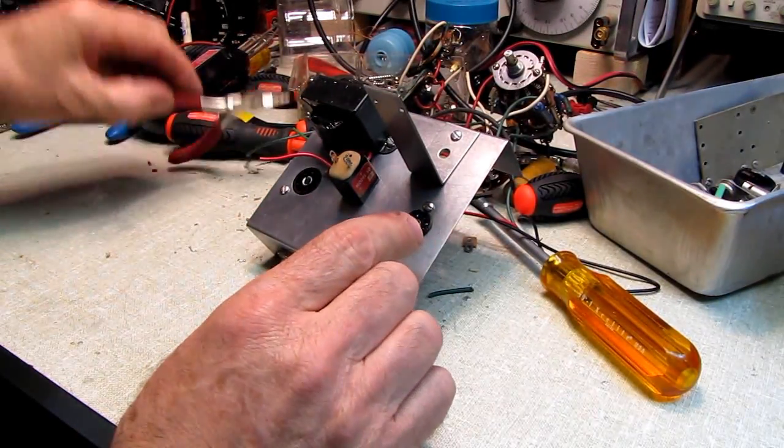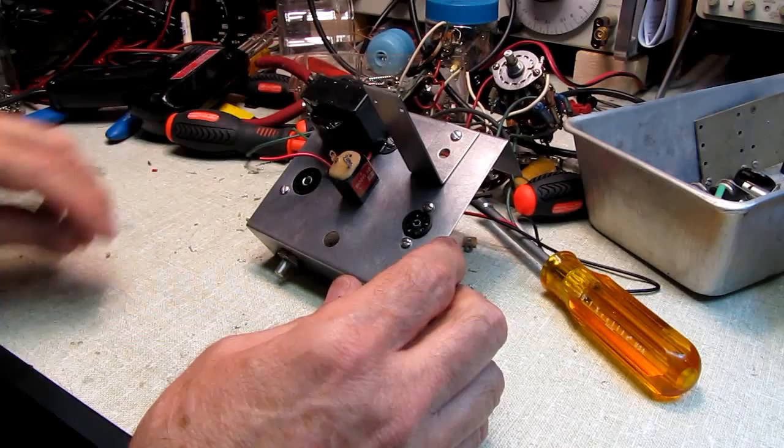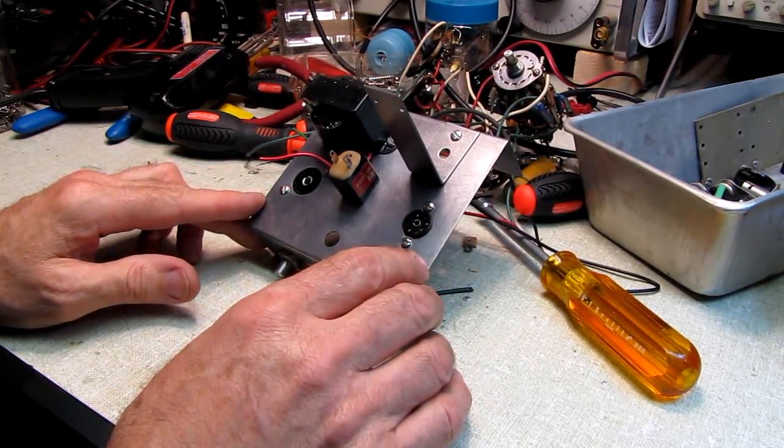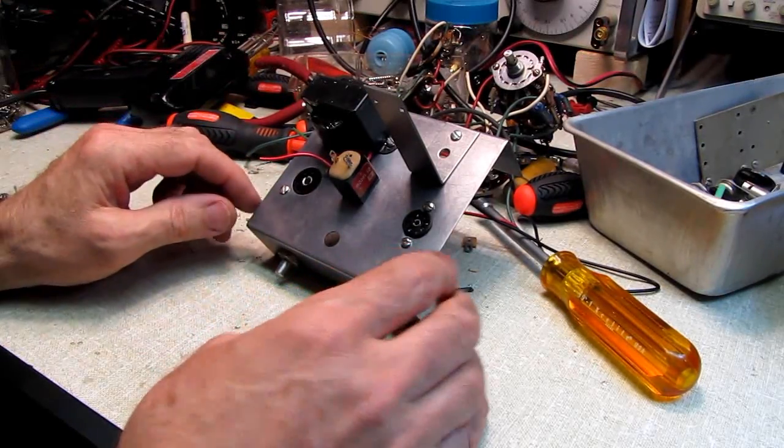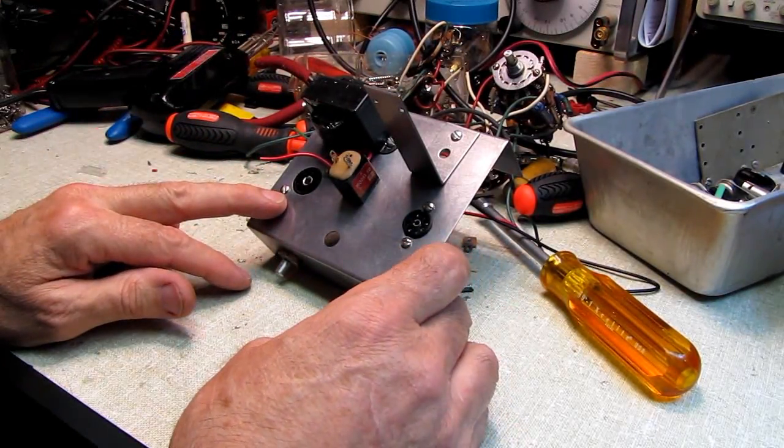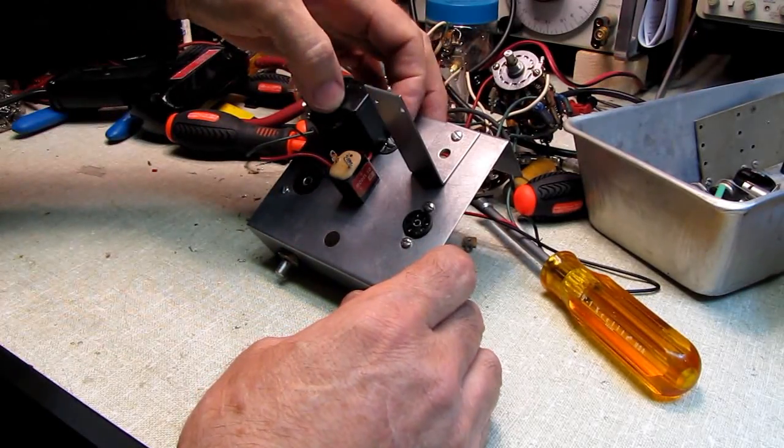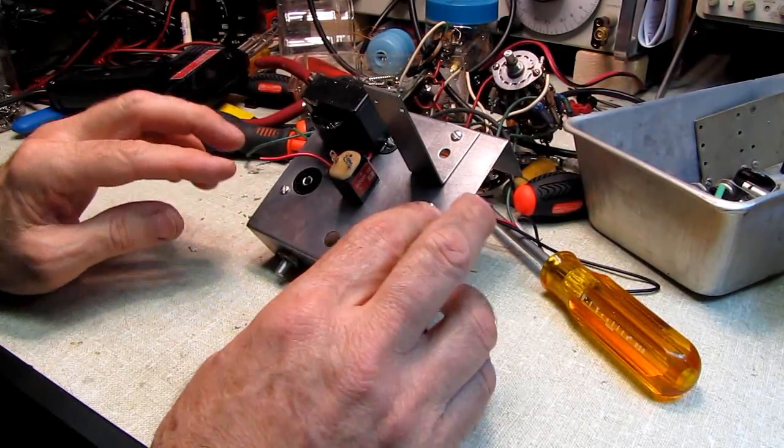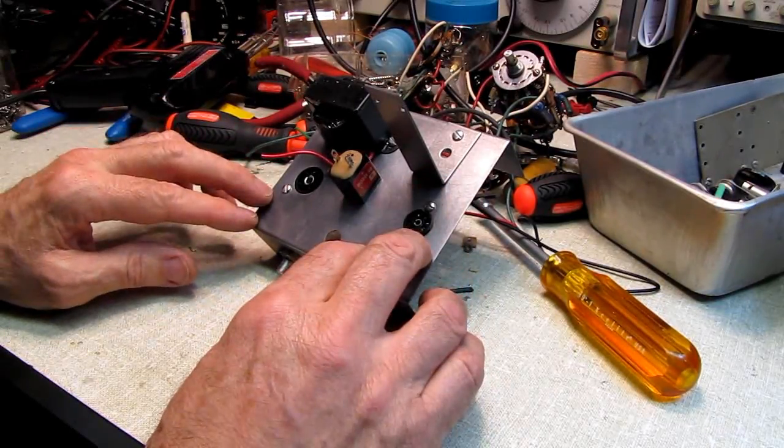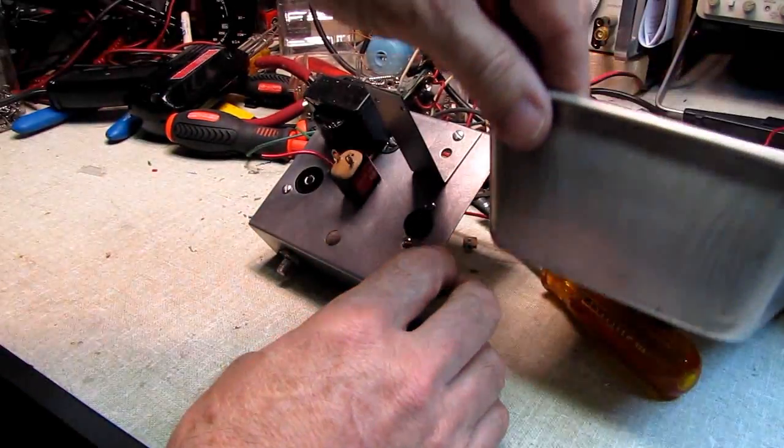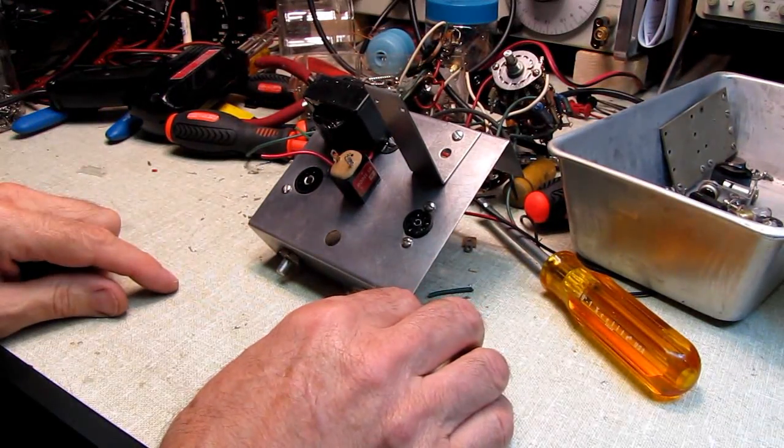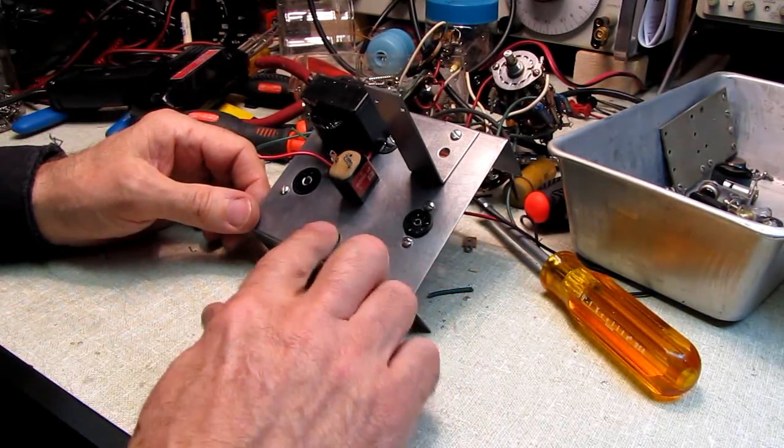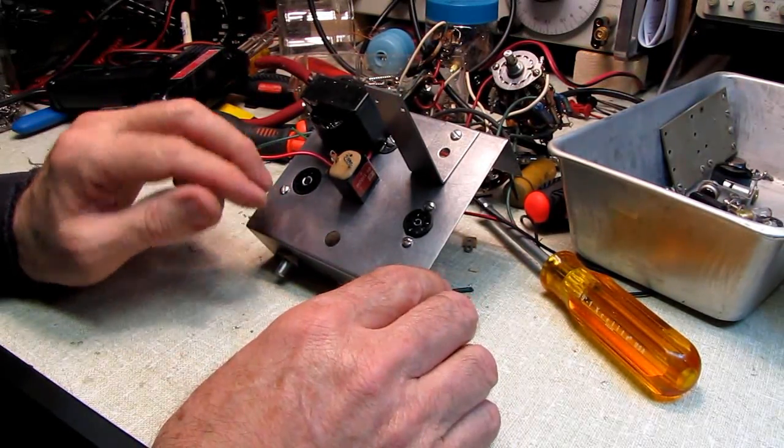In between each cycle I polished the surface with 4-0 steel wool. A lot of people I hear using Scotch-Brite. Scotch-Brite, in my opinion, is far too abrasive. It's going to leave scratches on the surface and probably take some of the plating off in the process. 4-0 steel wool is designed for polishing. And the surface finish, as you can see, came out just beautiful.